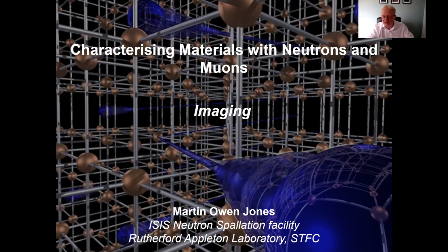Okay, so that's really not a strong point for me. I've never done any experiments looking at defects, but given the resolution power of diffraction experimentation, we can get information on the quantity of defects if you're talking about non-stoichiometry within solids. If you're talking about things that perhaps you would look at most commonly by high-resolution electron microscopy, such as slip defects or Frenkel defects and things like that, that is much harder for us to do with diffraction techniques. There have been some studies where things like that have been done, but it is a very niche type of experiment to do. You have to have a really good reason to want to try and do that by diffraction rather than by electron microscopy, I think.